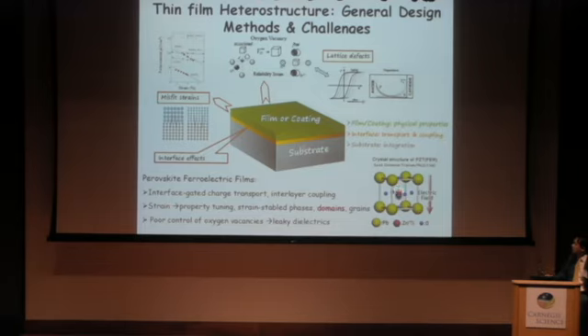In thin films, there are a lot of examples in bismuth ferrite oxide films. And also, you can tune the polydomain structures. Also in non-epitaxial films, for example, polycrystalline thin films, you can tune the grain structures by utilizing the strain. And the third aspect is the chemical control, the stoichiometric control of the thin film. Basically, if you grow an epitaxial film but you don't do good chemistry, you will get leaky dielectrics. So epitaxial doesn't guarantee you a good film. I won't touch this point, but just give you a general background about the design of a ferroelectric thin film.